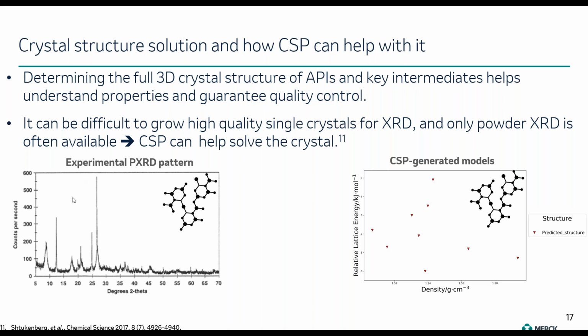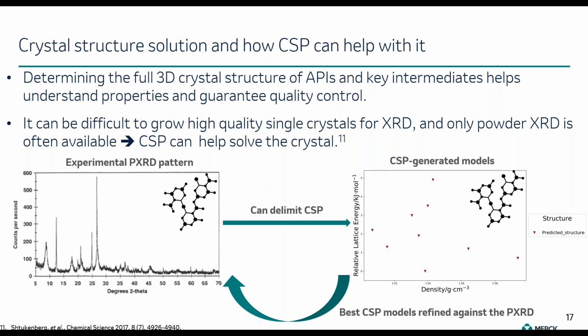How can we do that? If we have an experimental PXRD pattern and some CSP-generated models of crystal structures, it is possible to compare the simulated powder patterns of the crystal structures generated by CSP to the experimental PXRD pattern, and then it's possible to refine some of the models that match this experimental pattern against it to get a full 3D structural solution.